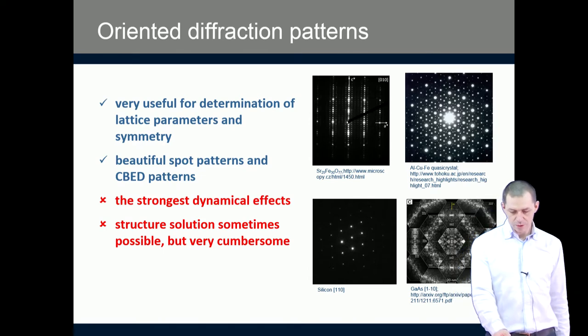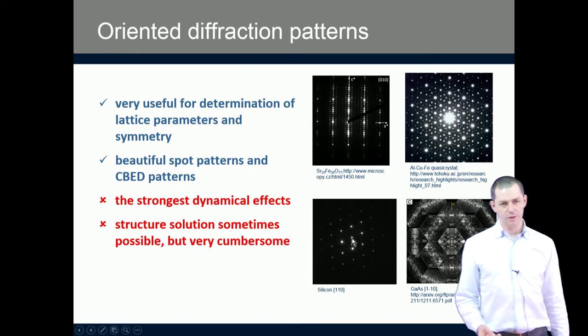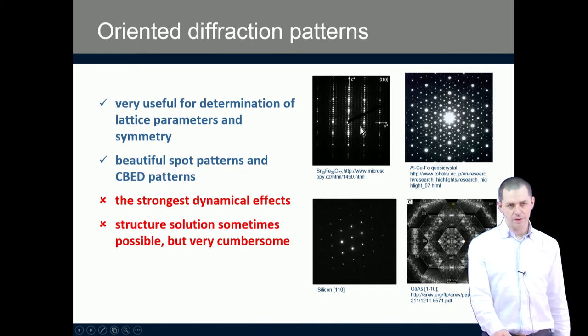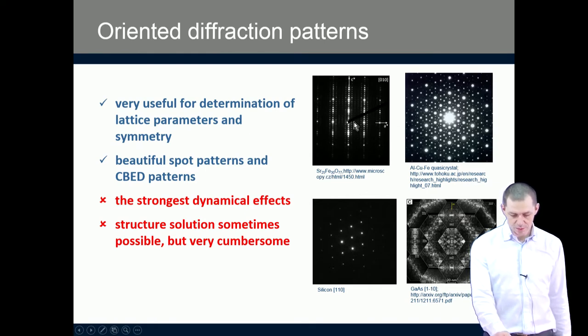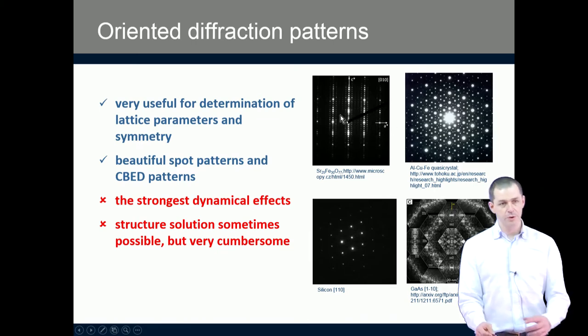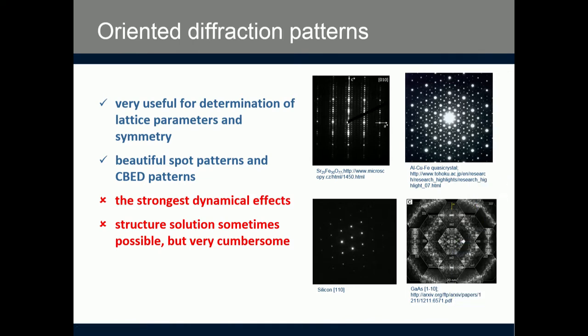information. So here you see a few examples of such oriented diffraction patterns, and you see, if you orient it properly, here in this strontium iron oxide you have the a-star vector in one direction, the c-star in another direction. You can measure directly from the picture the reciprocal lattice parameters. You also see that there are some satellite reflections in there. In this picture, this is a diffraction pattern from an aluminum copper iron quasicrystal. You immediately see there is a tenfold symmetry. It's very easy to interpret.